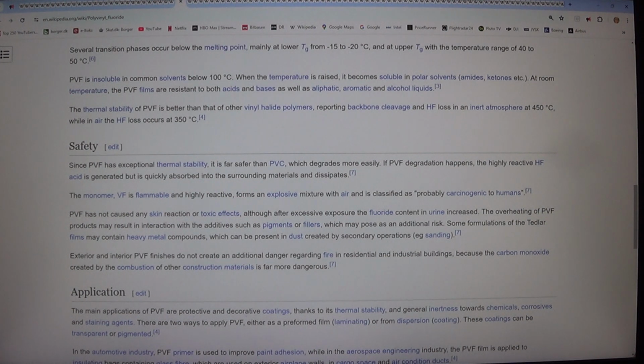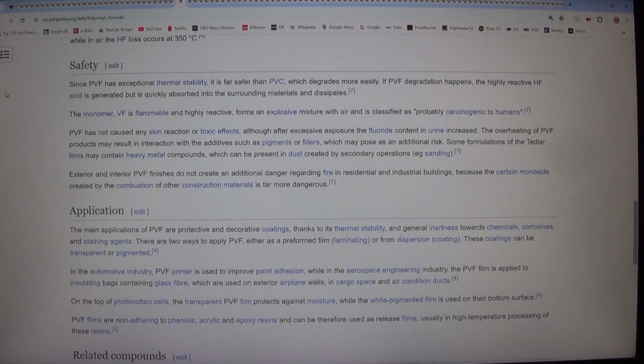Safety. Since PVF has exceptional thermal stability, it is far safer than PVC, which degrades more easily. If PVF degradation happens, the highly reactive HF acid is generated but is quickly absorbed into the surrounding materials and dissipates. The monomer, VF, is flammable and highly reactive, forms an explosive mixture with air and is classified as probably carcinogenic to humans. PVF has not caused any skin reaction or toxic effects, although after excessive exposure the fluoride content in urine increased. The overheating of PVF products may result in interaction with additives such as pigments or fillers, which may pose an additional risk.